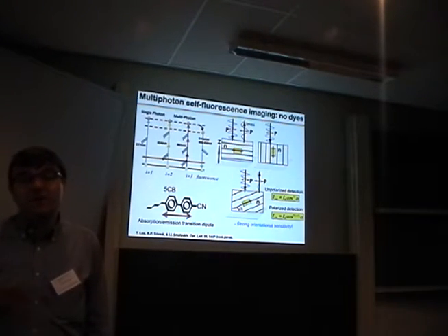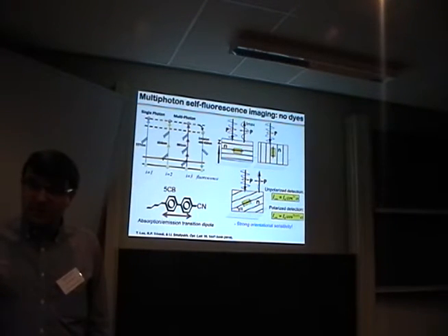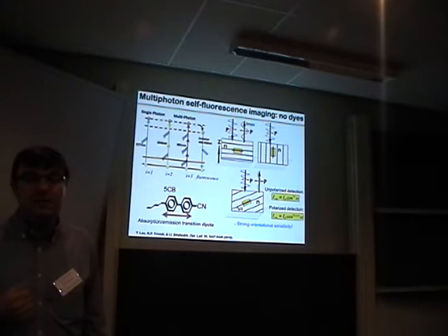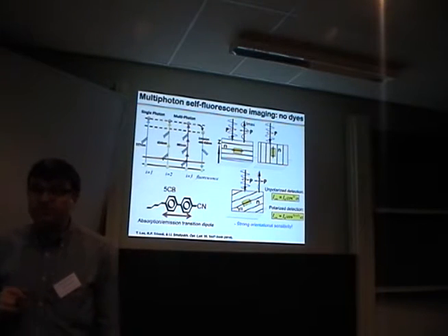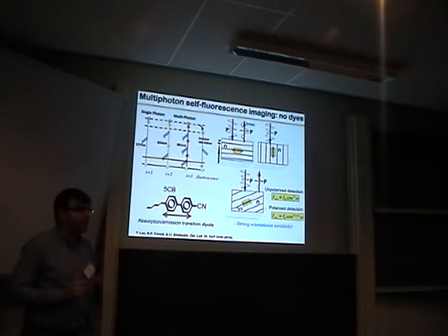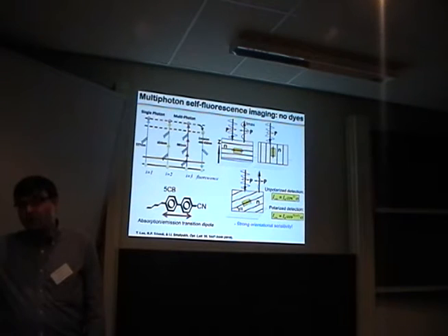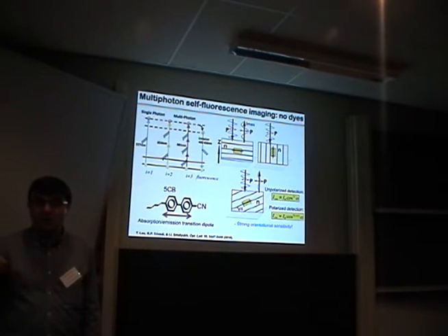Average laser power is still not a problem, but it gives you a better angular sensitivity, as you can see from this, and also a little bit better spatial resolution for the wavelengths of excitation because of the nonlinear nature of this process. So we mostly use 3-photon absorption. We do not go to 4-photon or so, even higher, just because that would require excitation further in the infrared. But yeah.